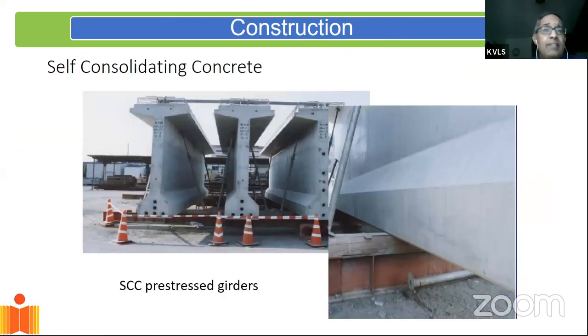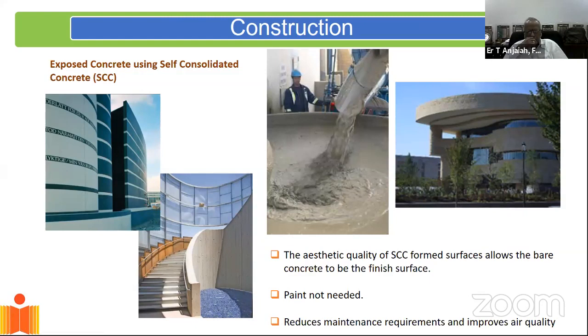Now, concrete made with this, self-consolidating concrete, is concrete which basically self-levels. It fills itself. It basically flows under gravity. I do not need to apply any vibration to get it to flow. The same precast girder, which was done with regular high slump concrete, is now done here with SCC. And you can see that concrete was able to fill all the small gaps between the reinforcement, the gap between the reinforcement and the formwork, and give us nice, shiny, smooth surfaces without any bug holes or any voids in the structure. Now, SCC, as it's called, self-consolidating concrete, basically flows like water, as it's shown here.